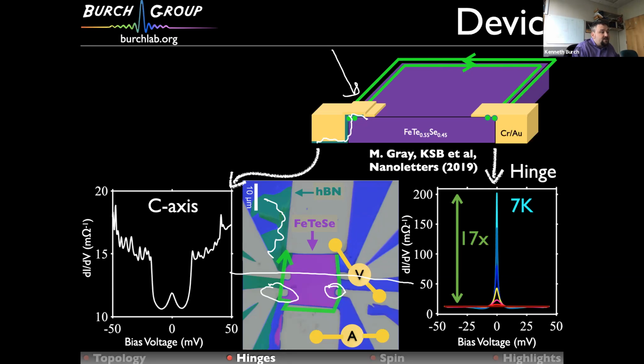And what you're really seeing is just standard Andreev reflection, where we're just too hot to really see it open up and look like normal Andreev reflection. Okay, and again, that's a 17x enhancement over the normal state. This very large enhancement you see at 20 mV, we think is just when we start tunneling outside of the TI gap. So we start to see more bulk states and we just get enhancements in tunneling. And then what looks like noise is actually not noise, but I don't have time to explain.